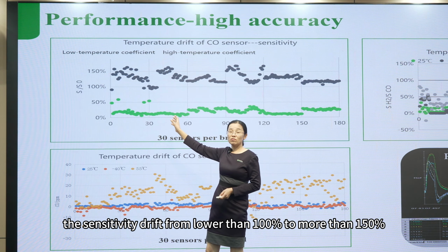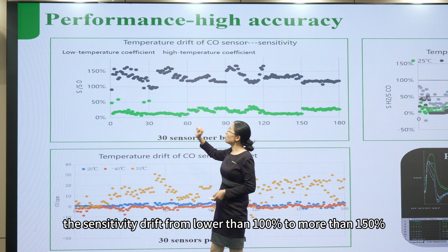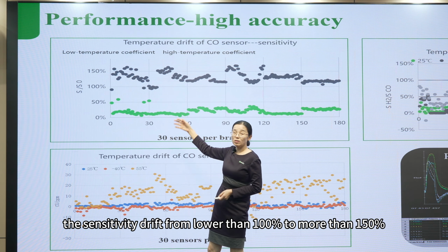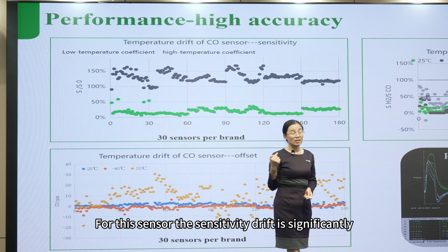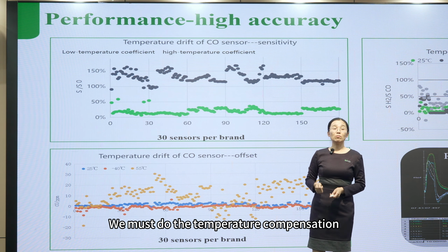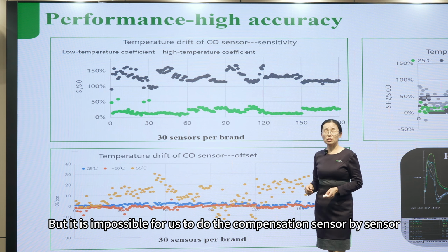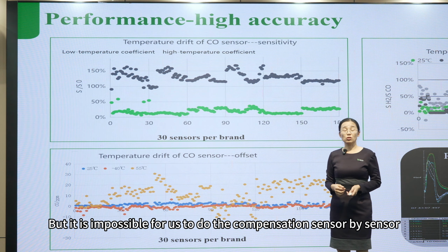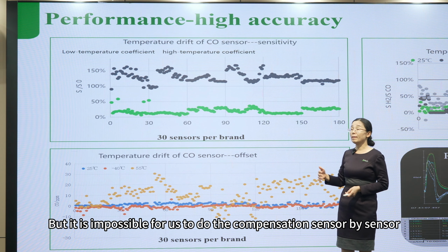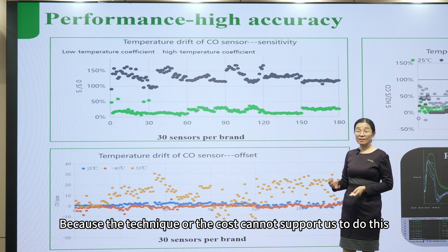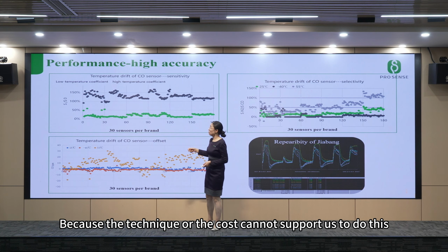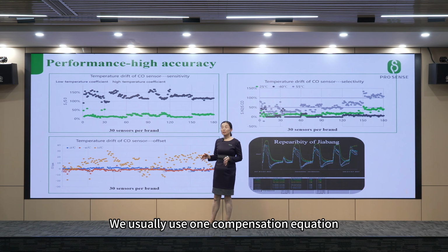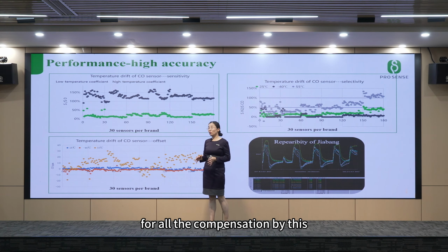The sensitivity drifts from lower than 100% to more than 150%. For this sensor, the sensitivity drift is significant. We must do the temperature compensation, but it is impossible for us to do the compensation sensor by sensor, because the technique or the cost cannot support us to do this. We usually use one compensation equation for all the compensation.